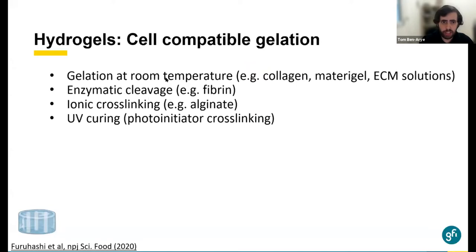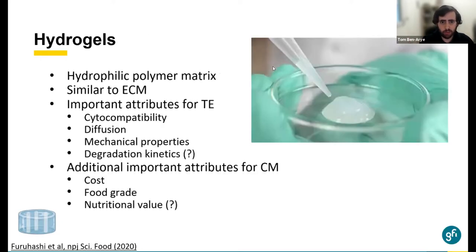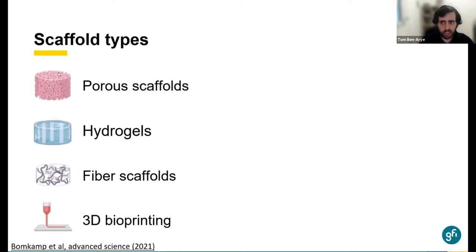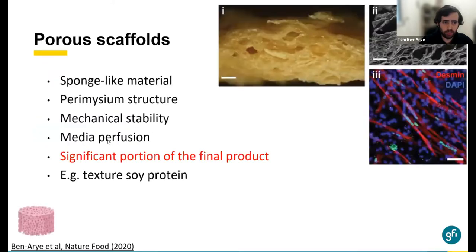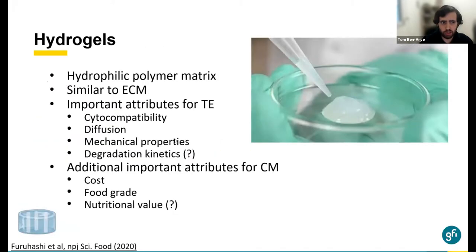Something important for hydrogels in cultivated meat or in tissue engineering in general is cell compatible gelation, because we introduce the cells into the gel solution before we solidify the gel. And if the gelling will hold in conditions that are cytotoxic, the cells will not survive. The scaffold itself that we saw before can be generated in toxic conditions. Just the final product should be cytocompatible. Whereas in hydrogels, not only the final product should be cytocompatible, the conditions in which it is produced should be cytocompatible as well. The gelation itself should be cytocompatible.